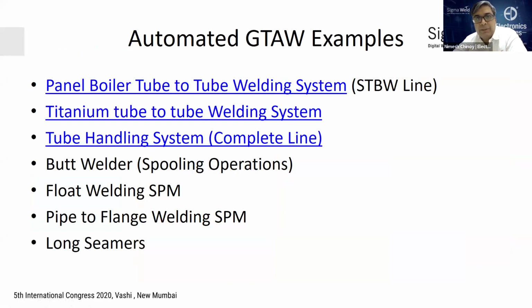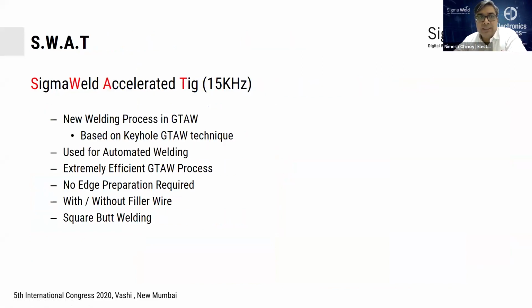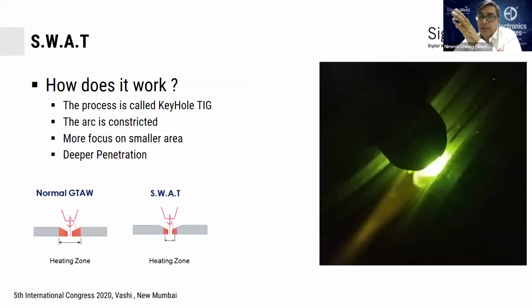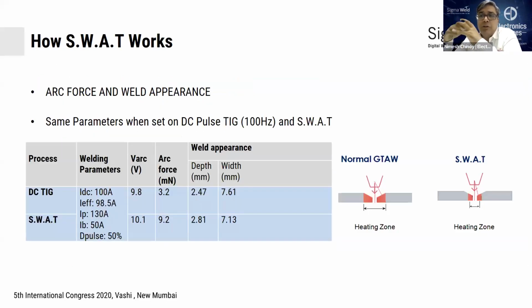A lot more examples for automated TIG welding, but if there is any specific one that you need, we can discuss that. Speeding up TIG to a different level where you call it SWAT, Sigma Weld Accelerated TIG, wherein we create a keyhole, narrow the arc, and go deeper. The arc force, when you narrow the arc, is so high, it's almost 3 times the regular TIG welding arc force.